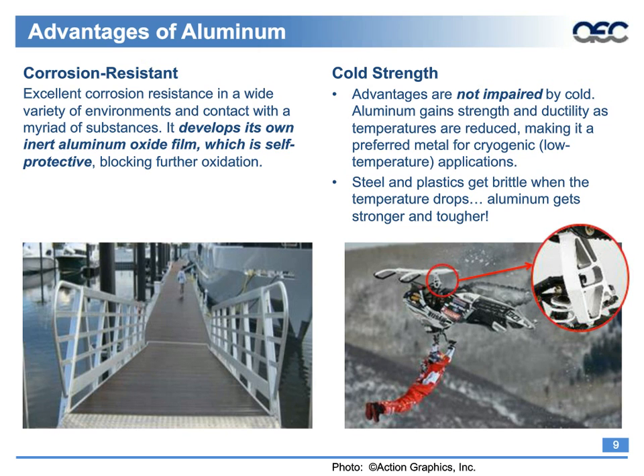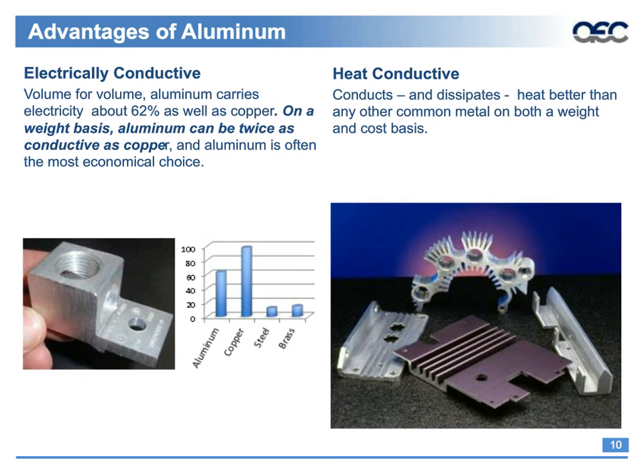Another advantage of extrusions is that they're not impaired by cold. They actually get stronger and tougher as it gets colder, which is kind of the opposite of steel and plastics. And I love this photo because it shows some crazy person upside down in a snowmobile, and you know in a while he's going to flip that thing around and land. And when he lands, the back end will hit, and then it's going to slam forward on the skis. And what's keeping that ski from collapsing is that aluminum extrusion that's shown in the call-out bubble. So it gets very, very good cold strength.